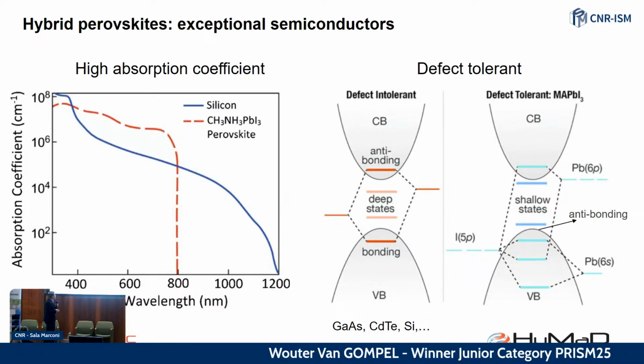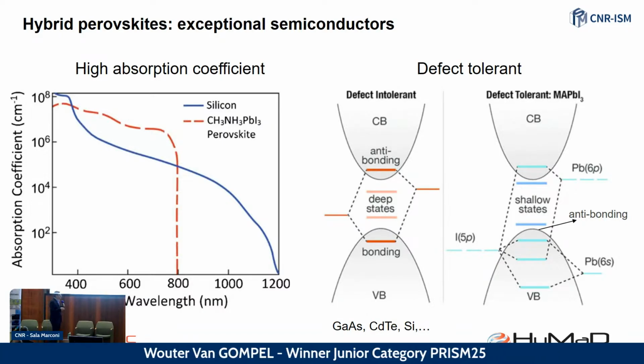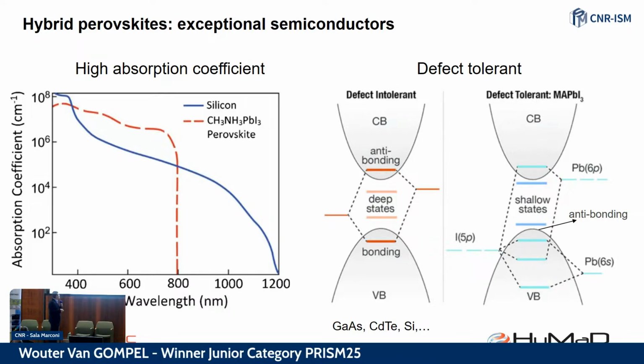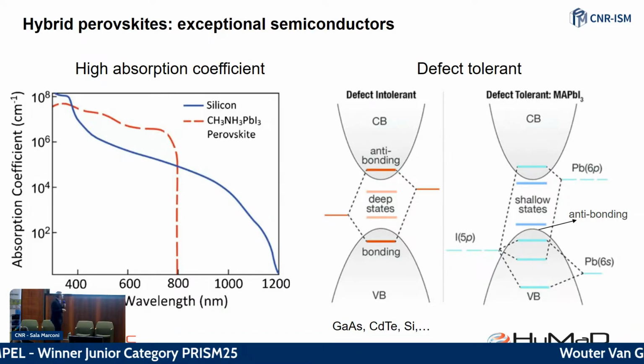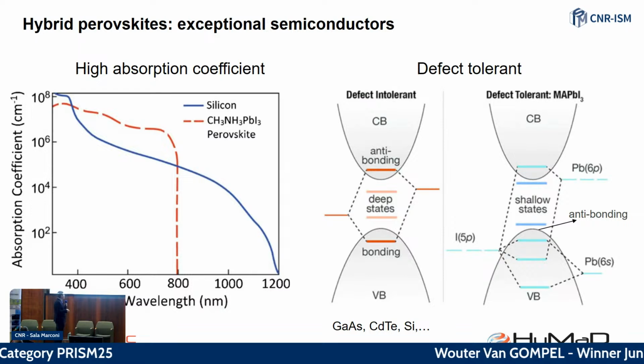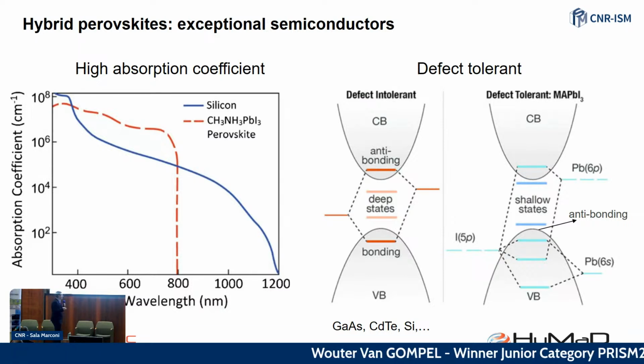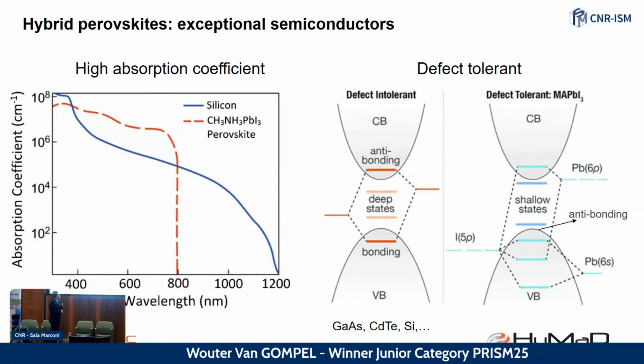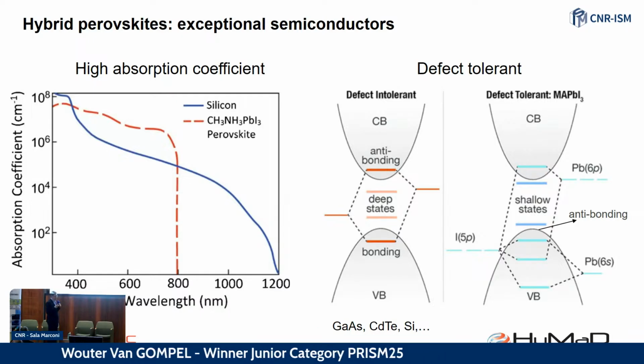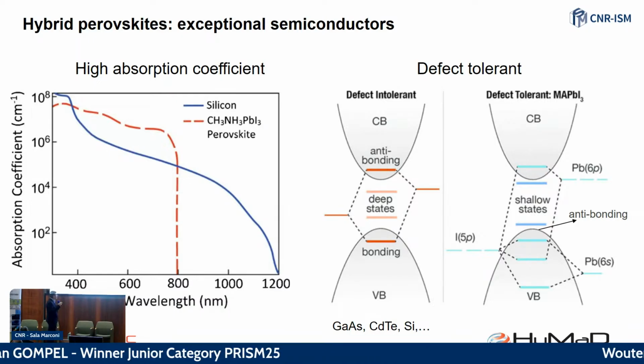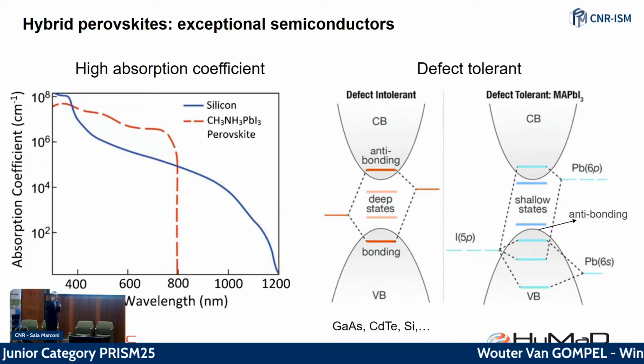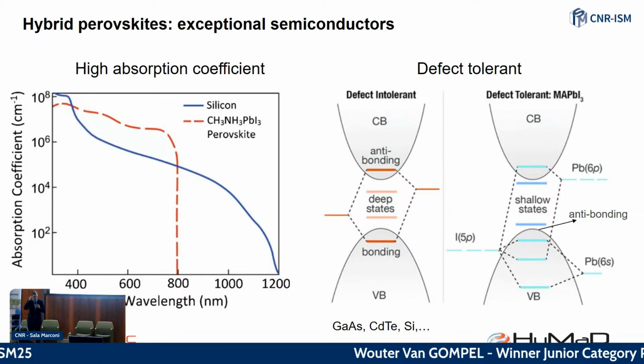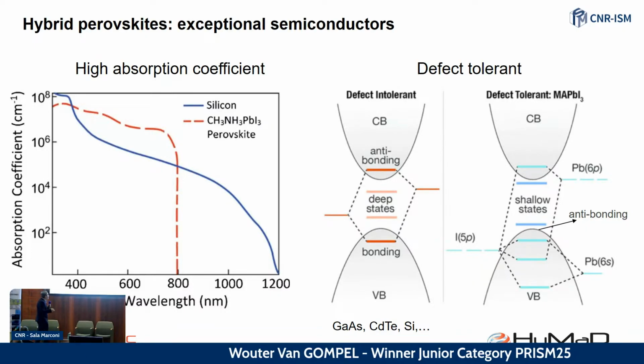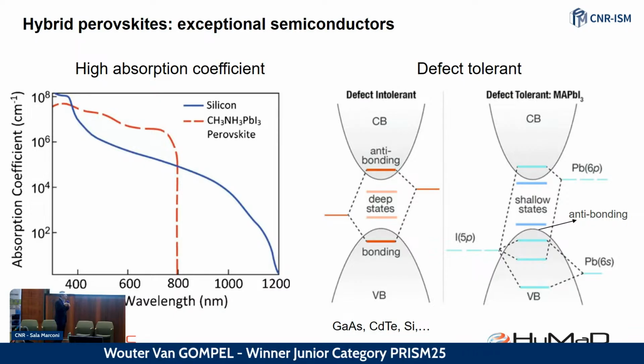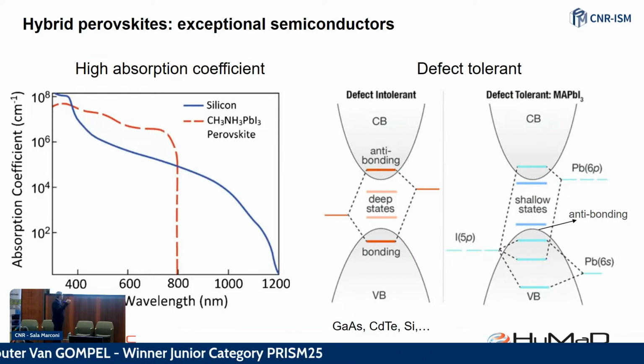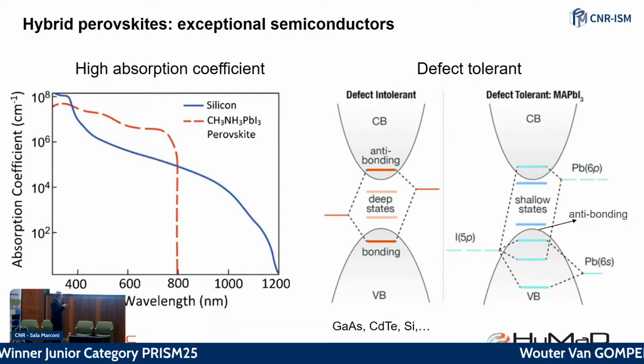The perovskites, on the other hand, have a quite specific band structure with the iodide 5p and the lead 6s contributing to the valence band maximum, and then the lead 6p and the iodide 5p contributing to the conduction band minimum. And you see here that the atomic states are either inside of the band or very close to the edges. And that is interesting because, even if you do have vacancies, they generate quite shallow traps. And they can just be detrapped via thermal energy at room temperature.